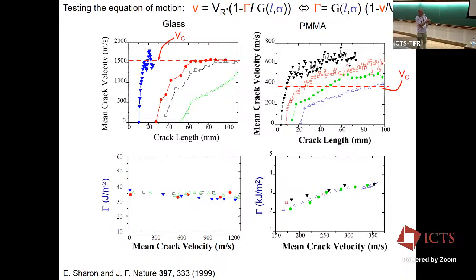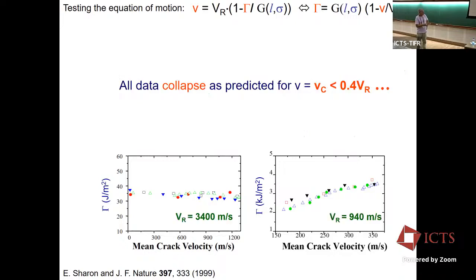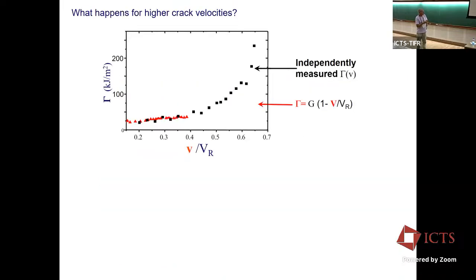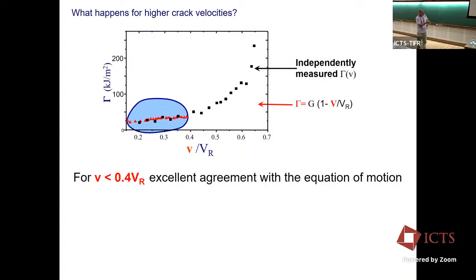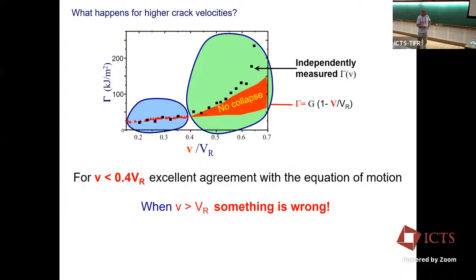Well, what happens beyond this critical velocity is that, okay, this is the same measurement here. This one's for plexiglass, I think. And this is independently measured gamma, which I can tell you how we did it, but it doesn't matter. And here's where our collapse is. And over here, if we use the equation of motion, it's a total mess. Something is wrong. We can't explain why the fracture energy all of a sudden goes up and the equation of motion totally fails. And this happens at a velocity which is about 40% of the asymptotic velocity.